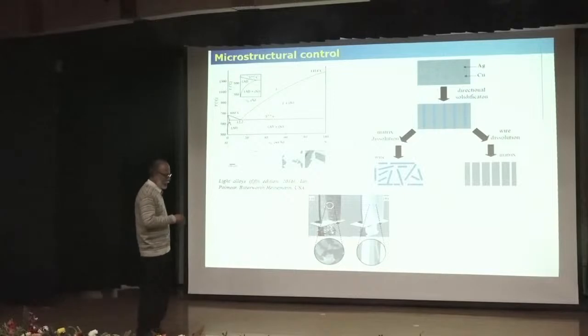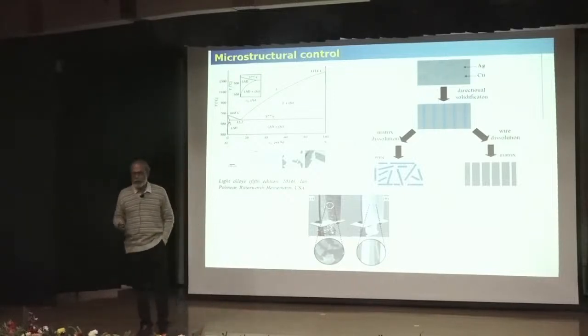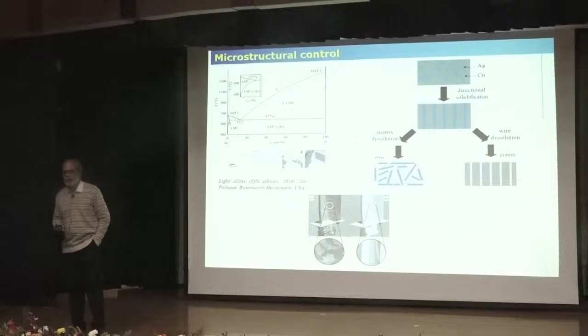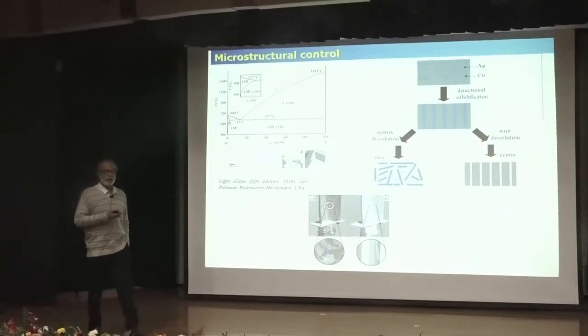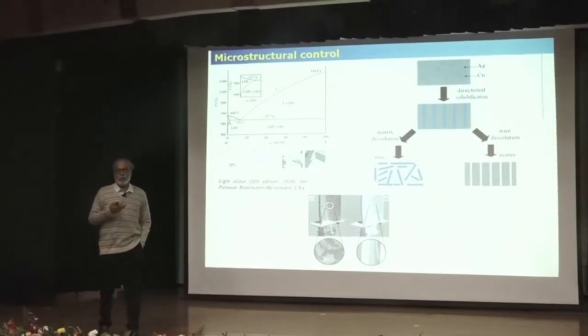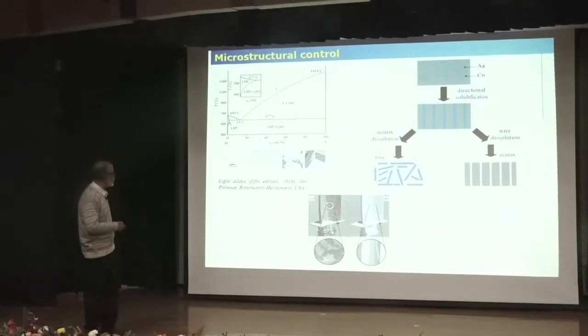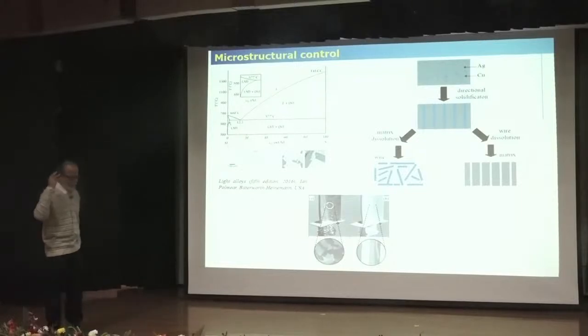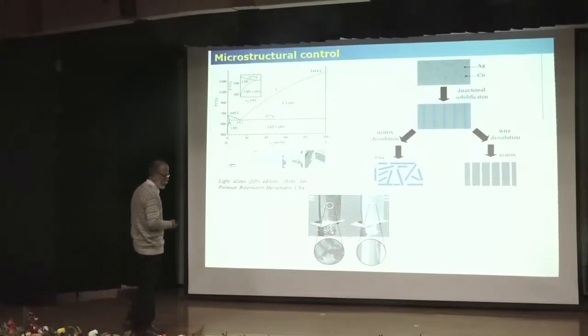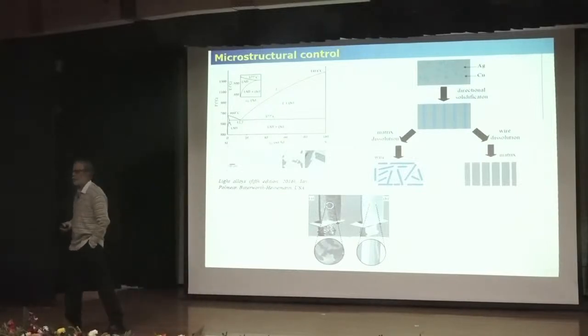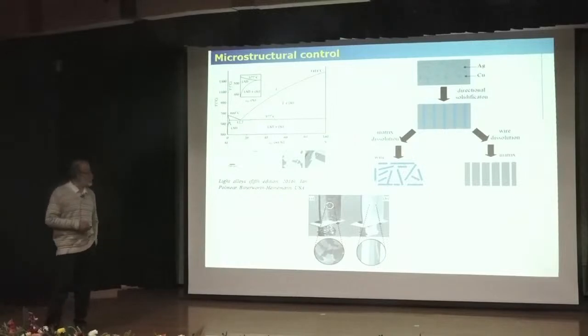So once that is there, the next step was microstructure engineering. People knew what is the driving force, how to manage undercooling, how to manage morphology. But how to manage the microstructure? Say for aluminum silicon alloy, which is a eutectic, basically there are 3 kinds of popular invariant reactions in solidification: eutectic, peritectic, and monotectic, right? So eutectic is most common. This is a common alloy, aluminum silicon alloy.